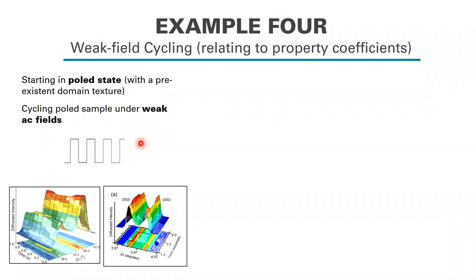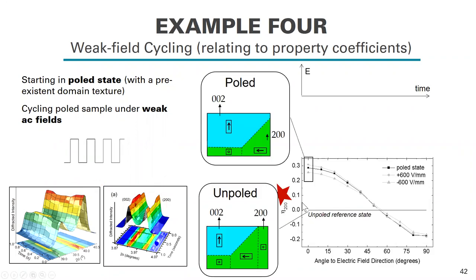Okay. And when we do these types of measurements, you can see measurable changes in the intensities. You may have to count for a long time, okay, or use a very high intensity source, but you can see changes in intensities under those weak field conditions. And so we represent that again as a pole figure. Here's eta on the y-axis. This is the unpoled reference state, okay? The poled state is shown as the black line. That's the domain texture in the poled state.